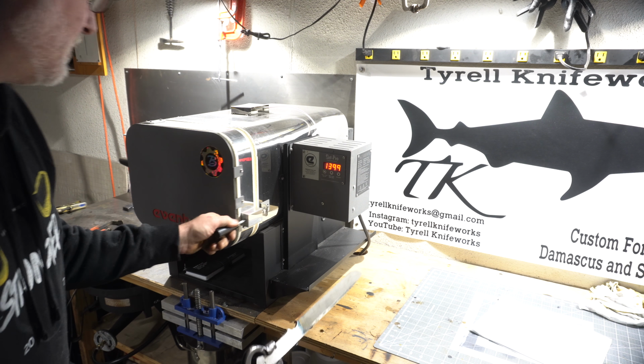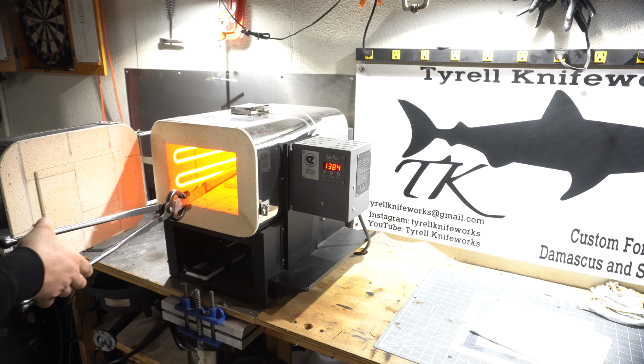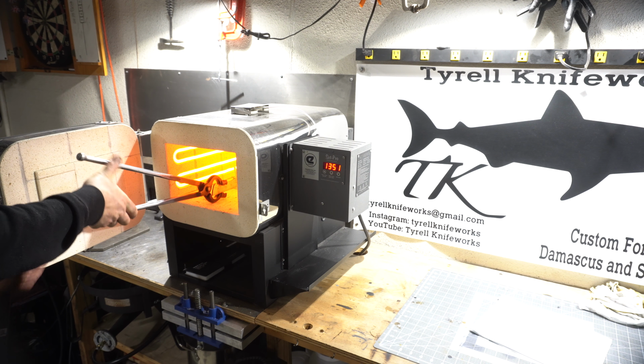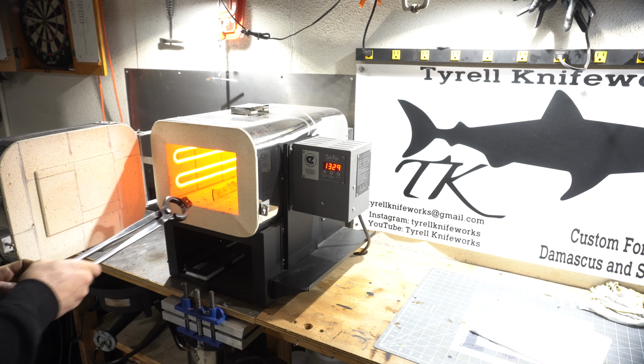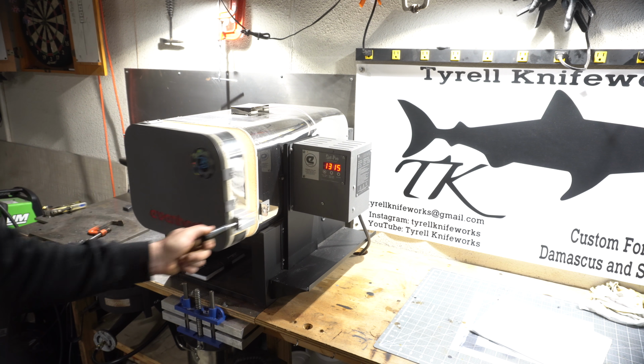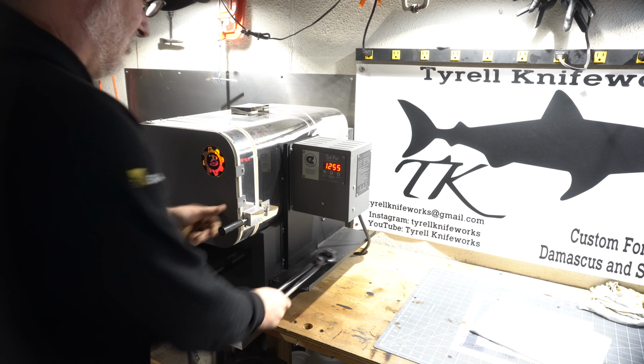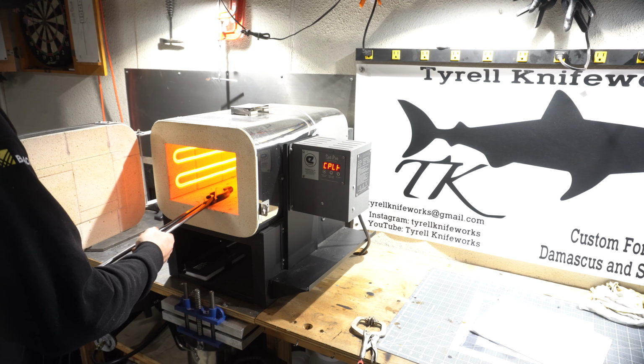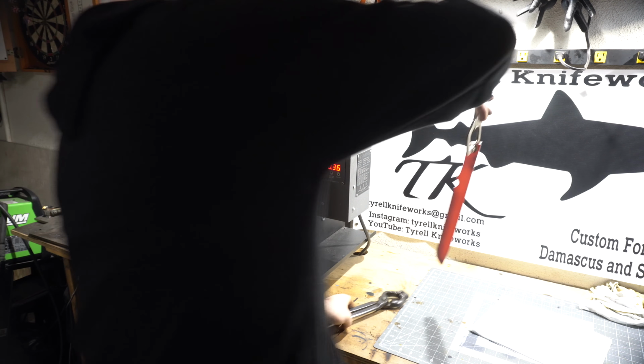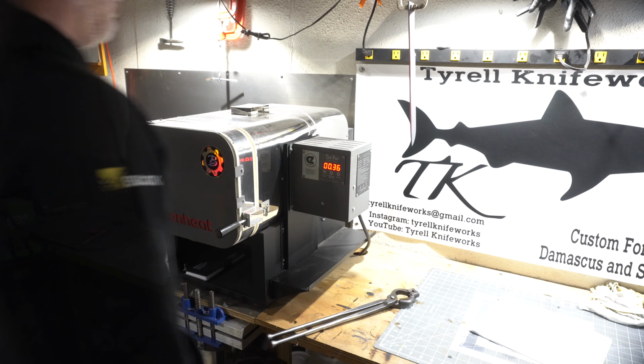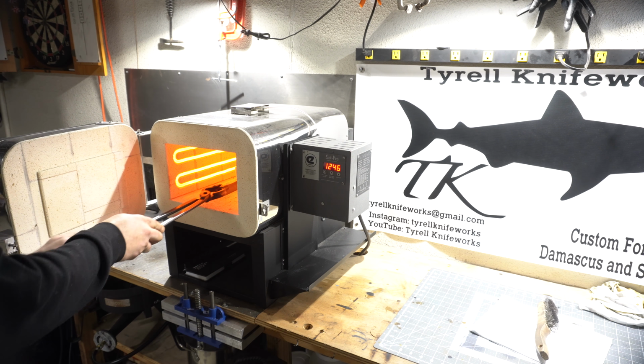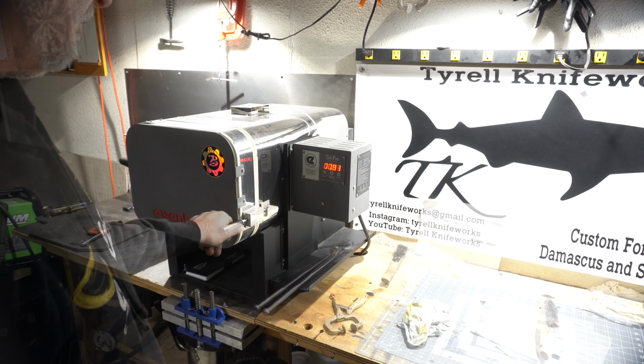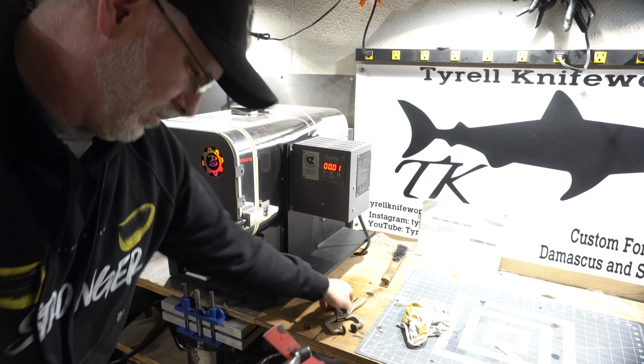Here's the first step. It's going in for the normalization at 1575 for 10 minutes. After it comes out, I just let it hang in still air until it cools to black and you can touch it. Now for the first of 2 grain refinement cycles. This time 1450 for 10 minutes.